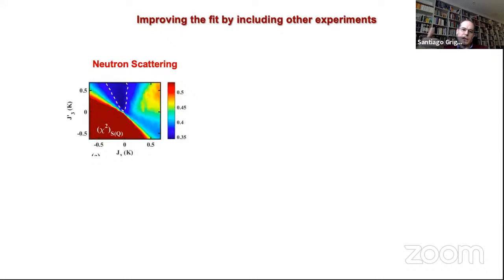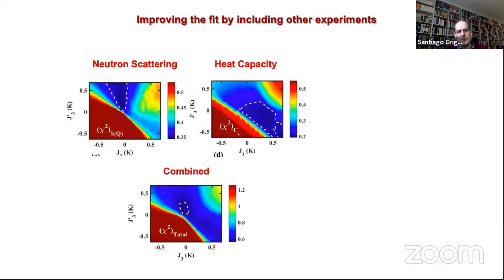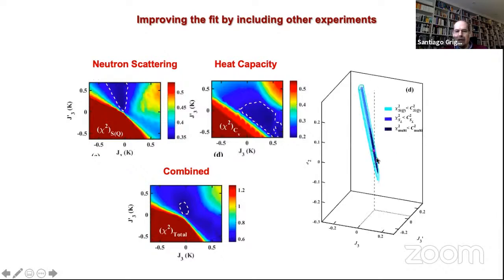Okay, so going back to the experiment, now that we did this fit to neutron scattering, we said, well, maybe we can add more information, like heat capacity or susceptibility. Now you can combine all these different sets of data and put them together, and you can narrow down the region where you get a fit to your parameters, right? This is J2, J3, and J3 prime. And this needle here is the region where the fit minimizes the difference to the experiments.